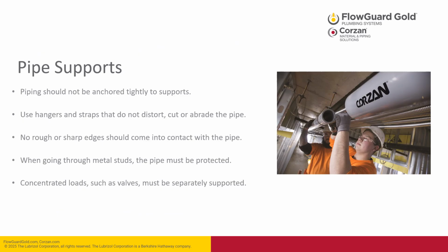When it comes to supporting the piping, it should not be anchored tightly to supports. This will restrict the natural expansion and contraction of the pipe and may damage the system. Use hangers and straps that do not distort, cut, or abrade the piping. And do not allow rough or sharp edges to come into contact with the pipe, which may damage the pipe's exterior. When going through metal studs, the pipe must be protected, and concentrated loads, such as valves, must be separately supported.